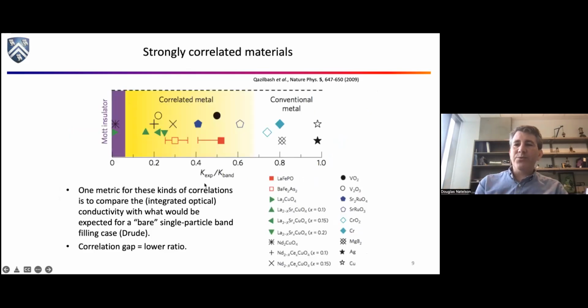When do you have, what are these? Both of those materials are examples of so-called strongly correlated materials. So you can have a metric for how correlated something is. Basically, you can do a toy calculation, turning off all the interactions, and figure out what the conductivity should look like as a function of frequency. And you can compare that to what you actually see in an experiment. And so if the ratio of the conductivity in the experiment to the no interaction version of the calculation is 1, you have weak correlations, right? And that's the example if you have silver or copper.